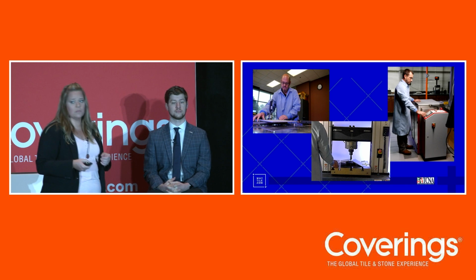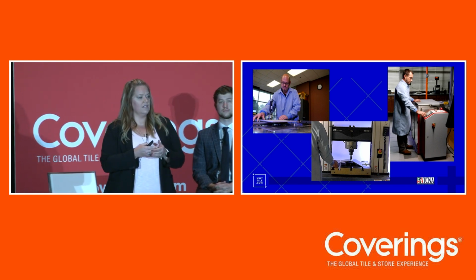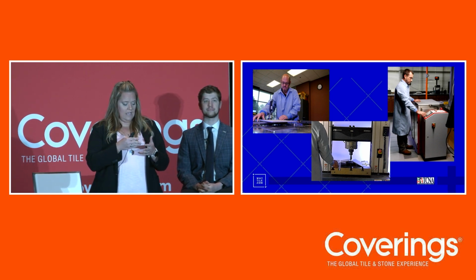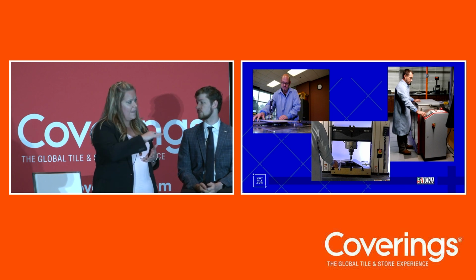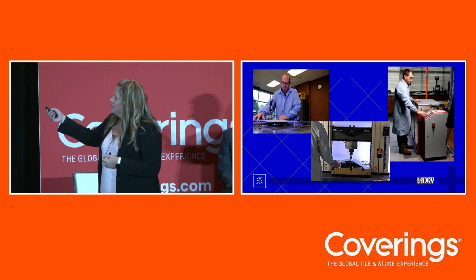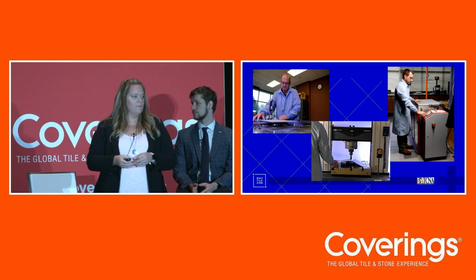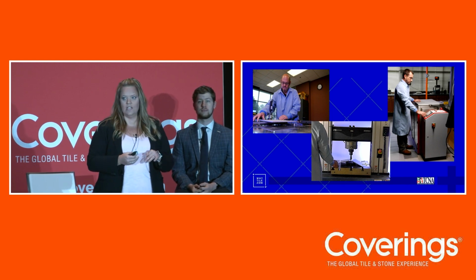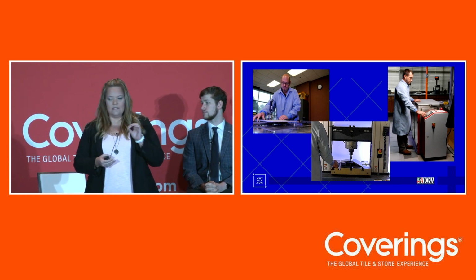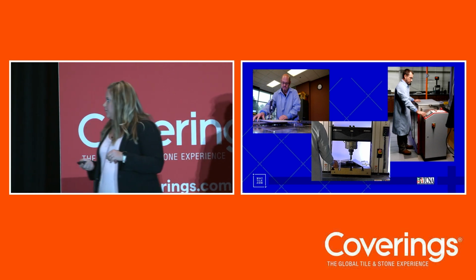In the center picture, that's breaking strength. So there's criteria based on the type of tile. So you have porcelain, wall tile, and just pressed floor tile. And they have different criteria for the strength. And then the other picture here is for water absorption testing. Many of you may already know, but one of the important tests in our industry is to determine whether a tile is porcelain or not. And the test that determines that is our water absorption test. So porcelain is less than 0.5% water absorption.